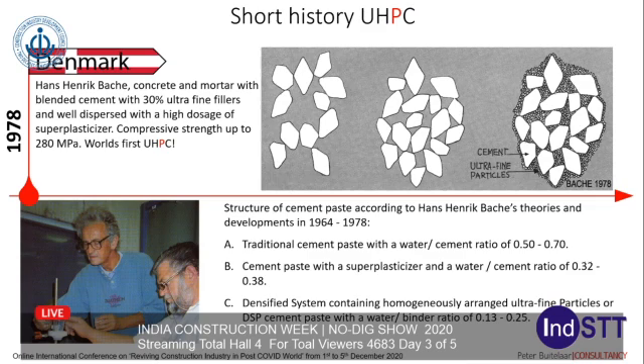Bache believed that the method to reduce the porosity was the use of very fine cement. But at that time, in the early 1970s, cement particles, and especially very fine cement particles, could not be dispersed in a small amount of mixing water due to surface forces. After the development of superplasticizers in Japan and Germany, a much denser packing of the cement particles became possible, and this resulted in a much lower water-cement ratio between 0.32 and 0.38.